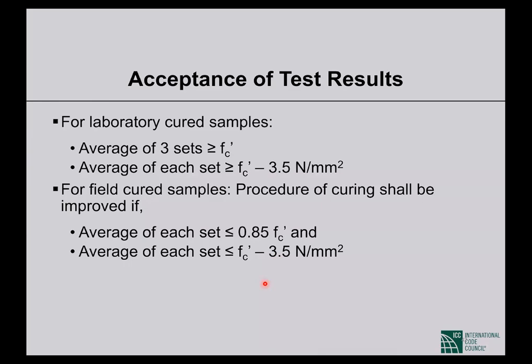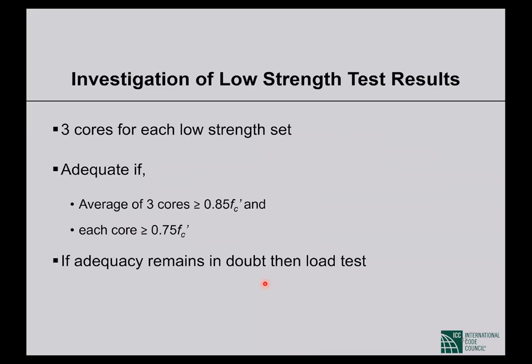Now, even after that, if the concrete strength is low enough that the criteria are not met, what to do? Just demolish the structure? No, you still have other things to do. You can cut cores, take core samples, and if the average of 3 cores is greater than 85% of fc prime, then that's okay. It doesn't have to be greater than fc prime. Just greater than 85% of fc prime is okay. And each core must be greater than 75% of fc prime.